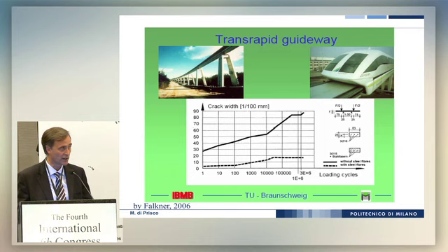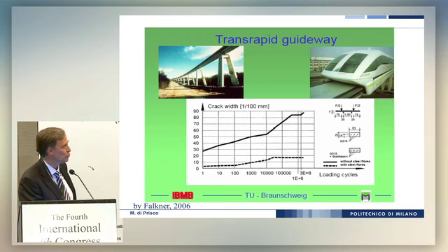Another subject well highlighted by Professor Falkner was also the fatigue, or better, if you like, the increase of the crack width with cycles. Loading cycles, in order to use in railway sleepers, he suggested this very simple test. You see there is a bending moment which is negative, and there is some reinforcement inside, and he measured the crack width evolution with the cycles in case of fibers and without fibers. So there is a strong difference, and this means essentially durability.